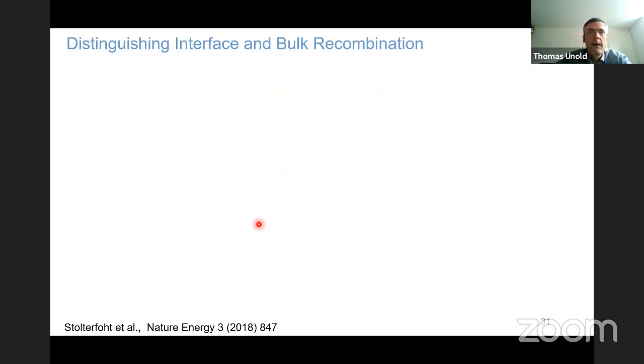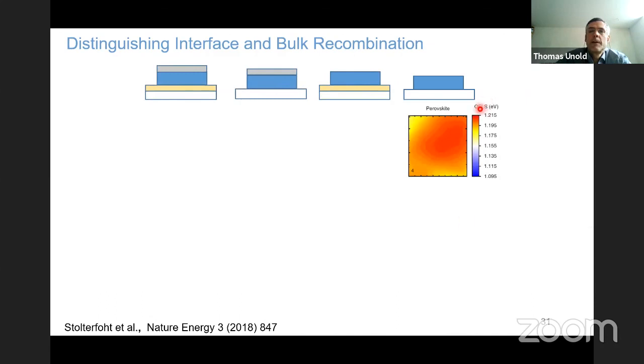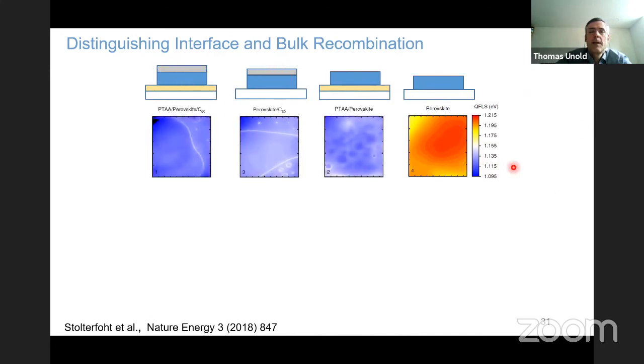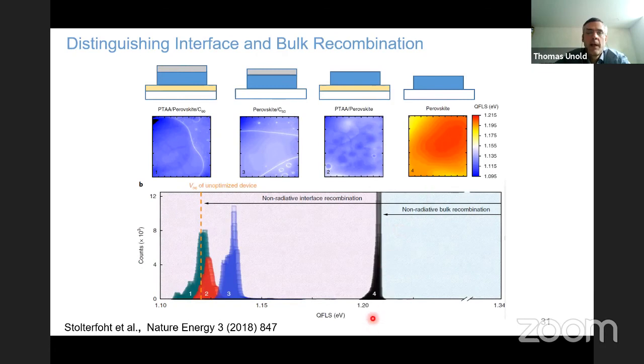So that brings me to the last topic, on distinguishing interface and bulk recombination. We did this study 2 years ago in different perovskite samples where we first looked at the perovskite layer on glass, and then with a hole transporting layer, and then with an electron transport layer, and then with both, and the whole device. And we measured the photoluminescence quantum efficiency and the quasi-Fermi level splitting. On the bare absorber we found this quasi-Fermi level splitting, and it consecutively decreased with adding these layers, which showed the contribution of interface recombination.